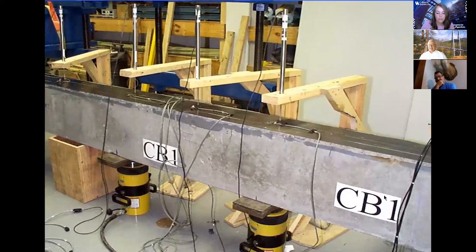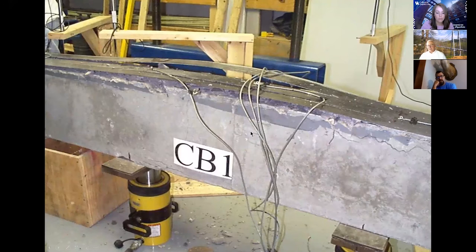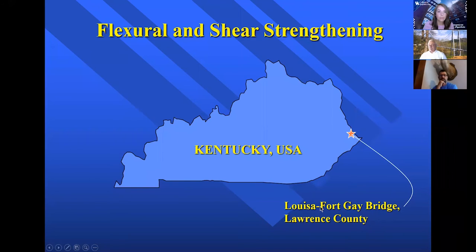So we did, again, extensive testing in the laboratory on it and collected data from it, right? To give you an idea on these beams, we tested one beam originally without any laminates on it, just plain reinforced concrete. And let's say it failed at 100,000 pounds. We took that completely damaged beam, straightened it, repaired the concrete, and put the laminates on it, and it failed at 150,000 pounds. It was 50% stronger than the original beam. So the material works very, very well. And it has been proven not only by us in the laboratory, but by many researchers all over the world.